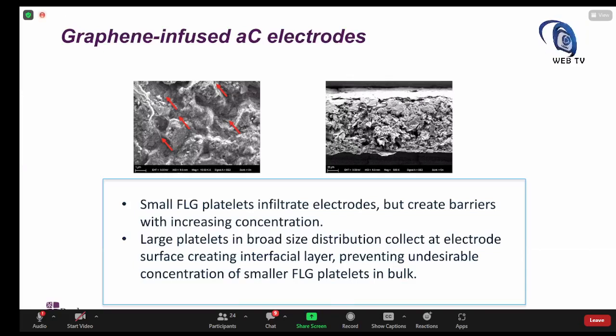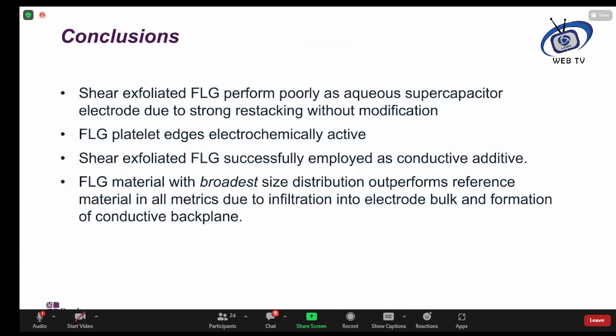So to draw conclusions, shear exfoliated few layer graphene alone is actually quite poor as an aqueous supercapacitor electrode, and that's due to strong restacking unless you chemically modify the few layer graphene. The edges of few layer graphene actually are quite electrochemically active. So ideally, if you want to use it in any kind of supercapacitor application, you should use platelets that are relatively small in linear dimension.